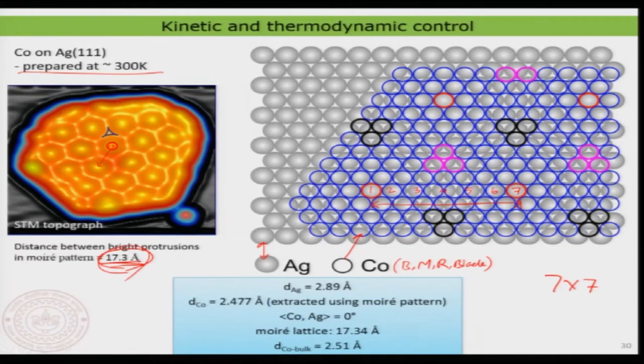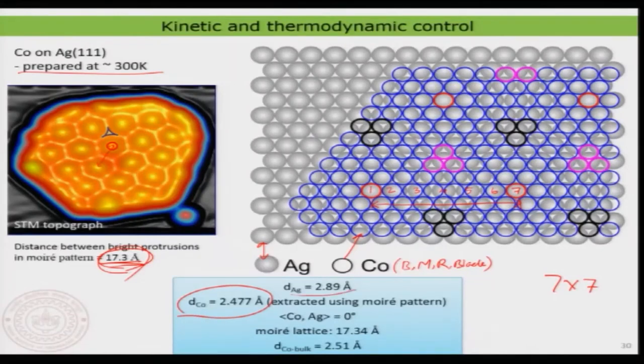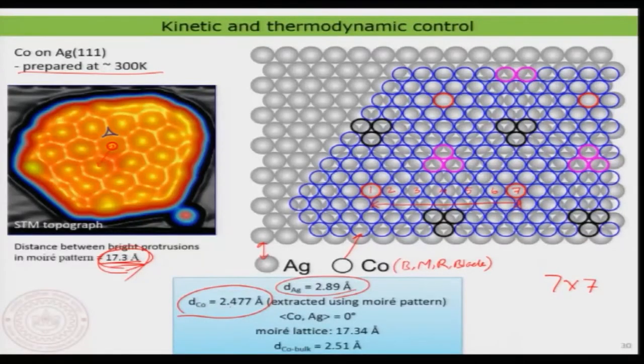So that's about 17.3 angstrom, and then I can basically back calculate what should be the distance between the cobalt lattice, because I am arranging them. In order to accommodate it nicely on the surface, I would recalculate the d cobalt-cobalt distance, keeping the d of the silver. So the silver lattice I am not changing, it is as it is from the bulk, because I am expecting the silver atoms are not relaxing, but because it's just one layer, I am expecting the cobalt atom to relax. And now you find that by slightly adjusting the bulk cobalt lattice, as you know, it is 2.51 angstrom, to 2.477 angstrom, I am nicely able to accommodate this kind of a super lattice, and then finally I can make a 7 by 7 supercell.